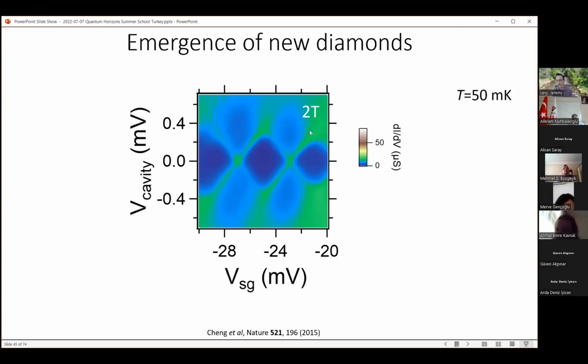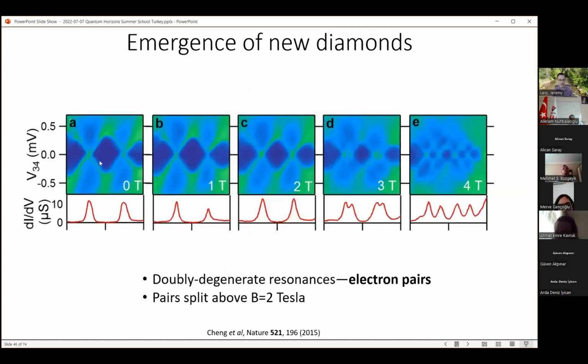But now I'm going to go to 3 Tesla. And what you'll see is that actually there's a new diamond forming between the big diamonds. And if that doesn't seem very apparent, I'll go to 4 Tesla, where now you see that they're all about equally spaced. And this is a very strange thing because the number of diamonds has doubled, right? So here is, again, the 0, 1, 2, 3, 4. If you take a cross section through 0 bias, you see that the single peaks persist up to 2 Tesla, and then they start to split.